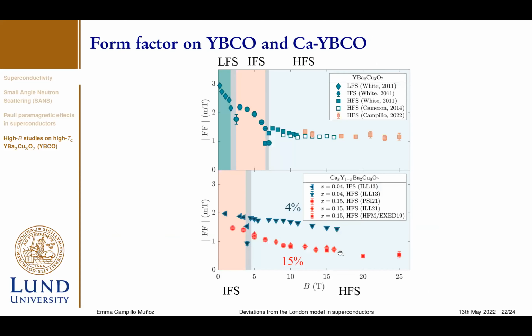Last but not least, since we were able to measure the vortex lattice, we also were able to measure the form factor of the 4% and 15% calcium doped YBCO, and also on our YBCO sample. Starting from the YBCO sample, we see that the form factor is not actually decreasing with field, and it's actually stabilizing at a constant value up to 25 Tesla.